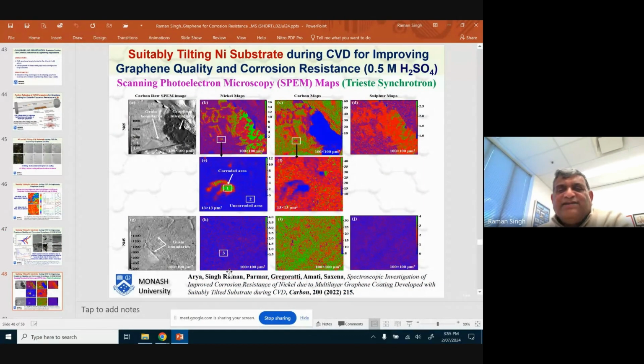We take a bit of pride in this particular work because this was the first time scanning photoelectron microscopy was used in corrosion research. It was done with the help of the Trieste synchrotron. What I'm going to show you is that when we had 5-degree tilted samples, there were disruptions in the coating. Because of the disruption, the nickel substrate was exposed, and when you expose that to sulfuric acid, it forms sulfide. That's why you have signal for sulfur and for nickel.